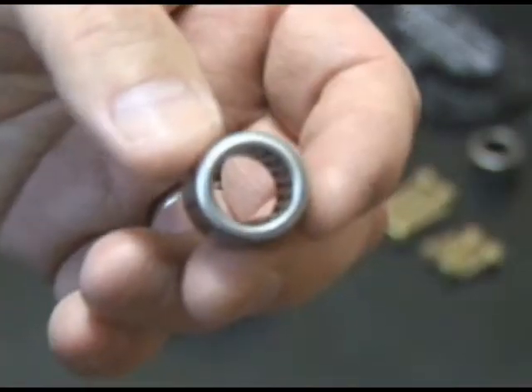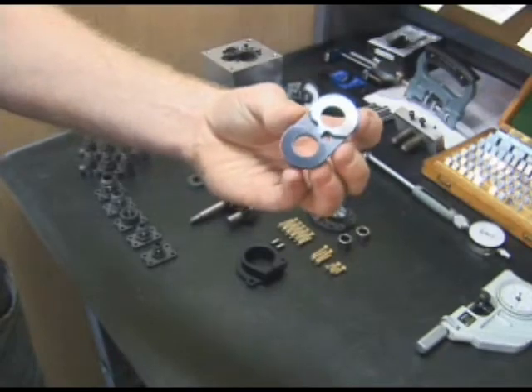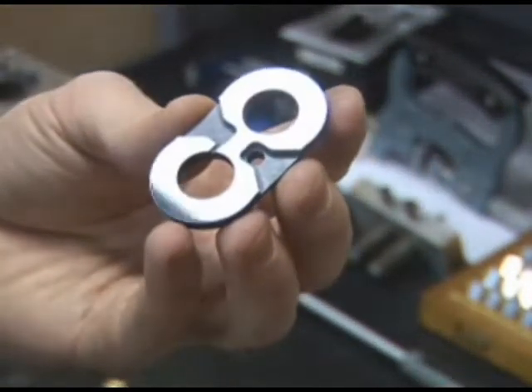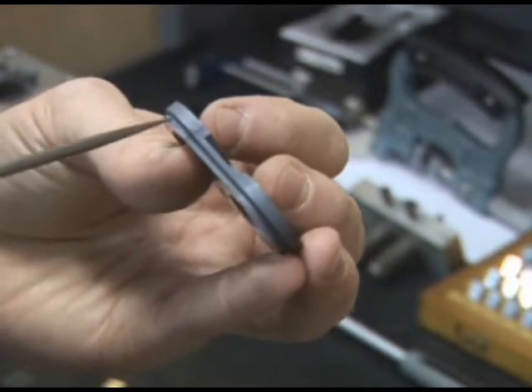Large diameter roller bearings are rated at higher load and higher RPM. After coating, plates are lapped into a 2 micro-inch mirror finish. A pressure passage hole puts pressure under the plate to lift it. Seal relief slot and lifted plate O-ring seal are also featured.